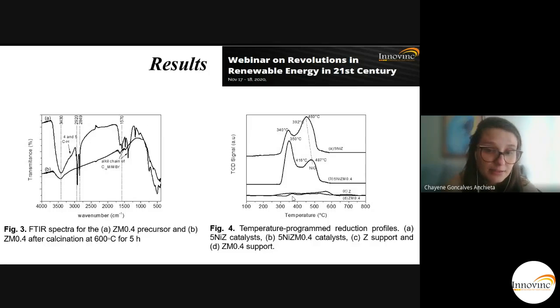Another characterization that we have done with these materials is the temperature programmed reduction profiles that was done using hydrogen, and we can see that after the nickel catalysts that are supported over zirconia synthesized using ionic liquids, we have a shift to higher temperature in the TPR profiles, which means that we have improved the metal support interaction when we used a nickel zirconia catalyst made by ionic liquid route.